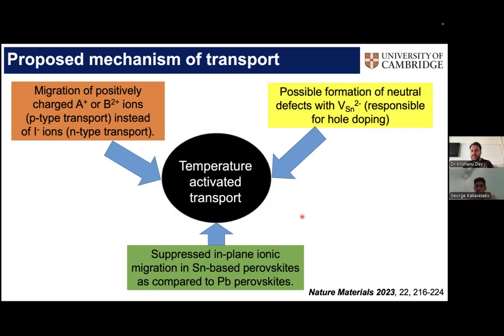But even if they move, we believe that because these tin-based perovskites have a lot of these tin vacancies, as I mentioned, these tin vacancies can easily ionize to give rise to holes. So then they are left with these negatively charged acceptor ions, which can form a neutral defect complex with these ions, A+ or B2+. As a result, you form some kind of a neutral defect complex which cannot shield the electric field anymore. So that is the two mechanisms for an FET structure, but you also see that even in an in-plane device without a gate, there is a suppression of the ionic migration in the tin-based perovskites.